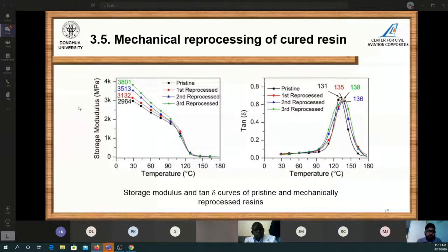So also we determined the mechanical reprocessing of the cured resin, and we determined the DMA, to see was there any change in the glass transition temperature as well. So there was a very negligible change in the glass transition temperature, but there was a smaller change in the storage modulus, because after the different heating recycle times, the resin was going to be brittle, like more brittle.